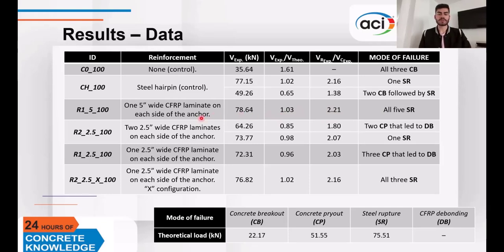Also, specimens with total width of reinforcement but distributed in two FRP sheets on each side of the anchor showed a variable behavior, as one of these specimens achieved steel rupture, but the other two evidenced concrete pry-out, which led to the debonding of the CFRP laminates. This shows us that concentrating the composite material near the anchor is more effective than distributing it.